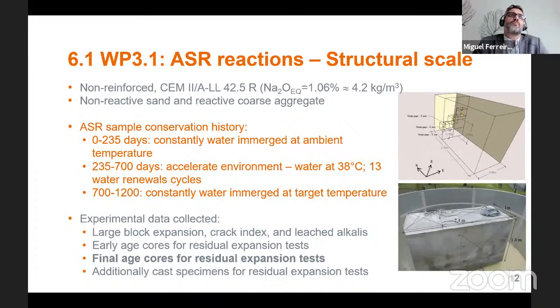And the data collected from the block are the block itself, the expansion, the cracking index, and the leached alkalis from the block. And this was taken from measurements of the pool water. We have early age cores for residual expansion tests. These were taken at 235 days of age. Final age cores for residual expansion tests as well.